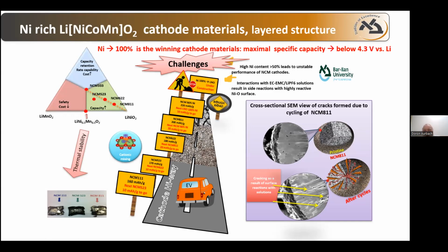What is nice about this family is that we can reach the maximal capacity upon charging up to 4.3 volts versus lithium. This means that in order to extract the maximal capacity, we don't have to endanger our electrolyte solutions. But as we go up and up with the percentage of nickel, the road becomes more problematic. We have cracking, we have instability because of the phase transition. And usually when we have electrochemical instability, we also have thermal instability.